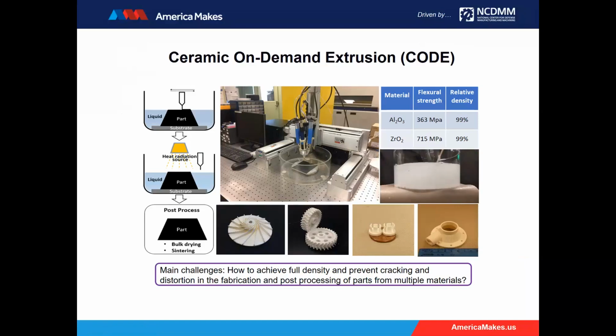And then the drying is done by radiation heating from the top. This is to prevent warping and cracking. And we have shown that we are able to make parts from alumina and zirconia up to a relative density of 99%, which is very good. Very nice fracture strength. And also the materials can be mixed together to make functionally graded materials.